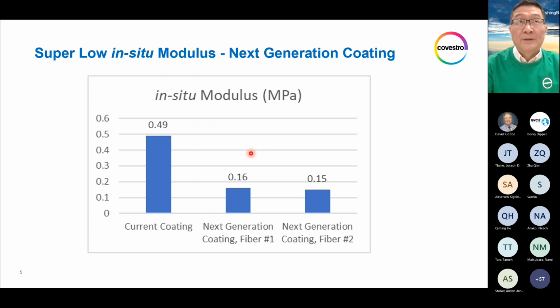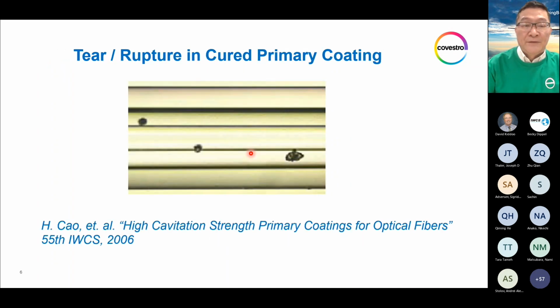However, just like with any change, there comes a risk. In 2006, we presented a paper at IWCS about the risk that comes with a very soft primary coating, because in material science, material strength goes hand in hand with mechanical properties, for example Young's modulus. When we reduce Young's modulus gradually over time, there's a risk of losing strength. For example, we have observed some kind of tear or rupture in the cured primary coating.